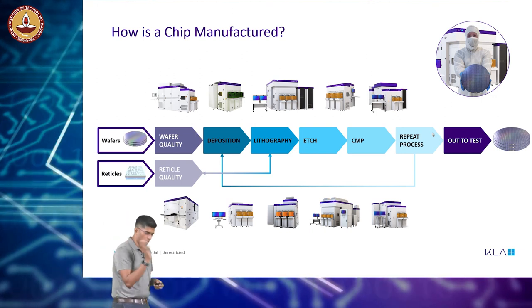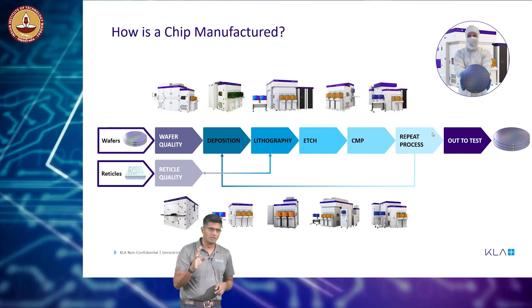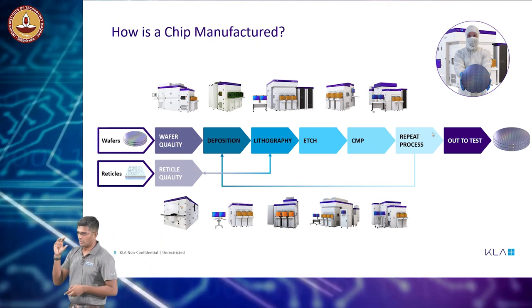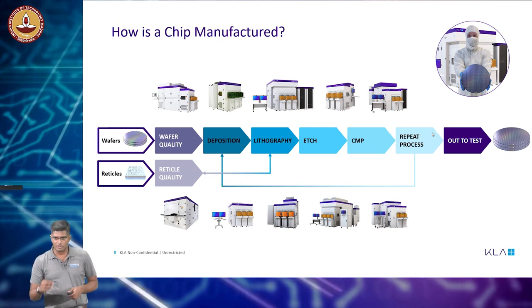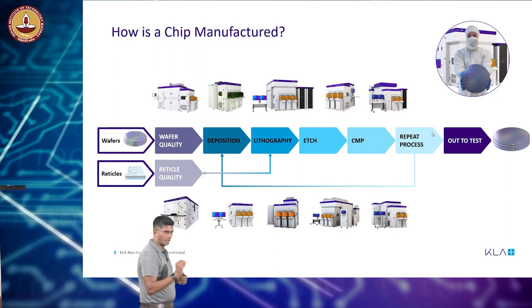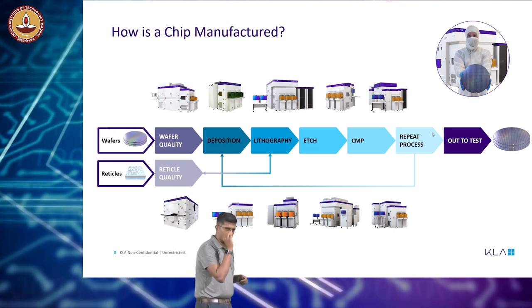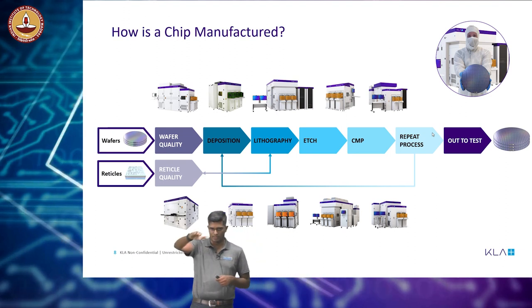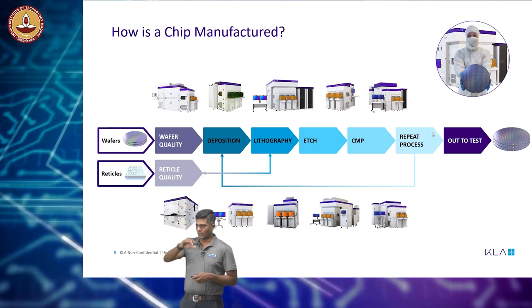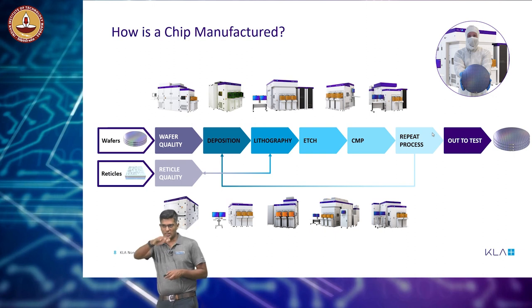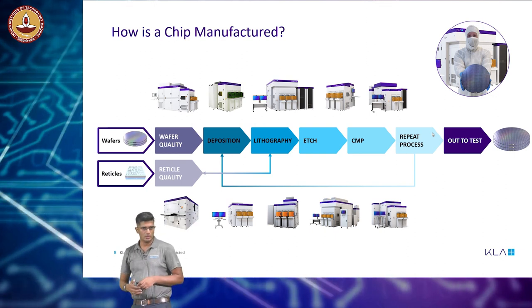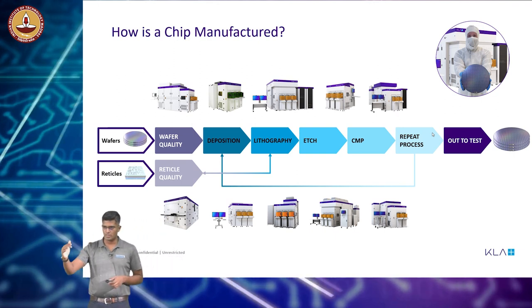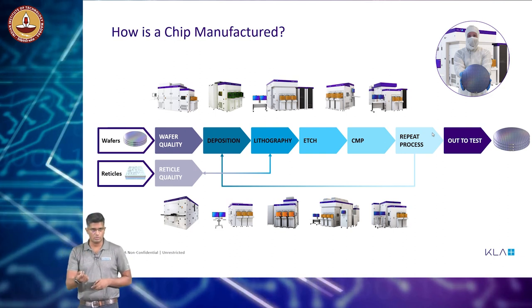There are two types of tools — one is called a metrology tool, one is called an inspection tool. Fundamentally, process control is about making sure that the process with which manufacturing is happening is accurate. But the definition of accuracy is also loose, because in the angstrom era as you approach 5 nanometers, 1 nanometer, and sub-1 nanometer manufacturing, what you try to draw as a straight line is no longer a straight line — it is jagged because of quantum effects. You expect to draw a straight line in the circuit, but it is a jagged line, and up to a certain degree of variation can be tolerated by the circuit.